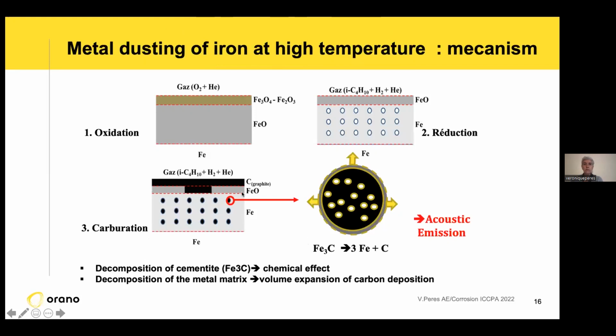So this is the metal dusting mechanism, as I showed you for the zirconium. In this case, we began with oxidation of the sample because of industrial conditions. We have an iron oxide at the top surface of the iron, which is here. And then, due to reductive conditions, isobutane, we have some reduction of the iron oxide previously formed, and some holes appear here. And then if we keep the reductive conditions, we have progressive insertion of graphite, of carbon, inside the iron, and a deposit of graphite at the surface.